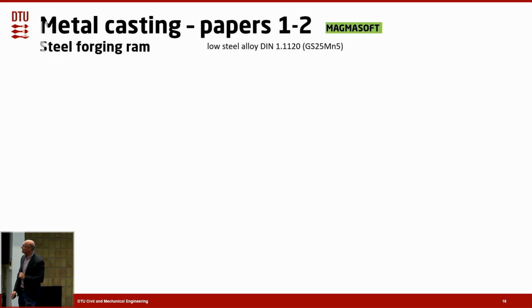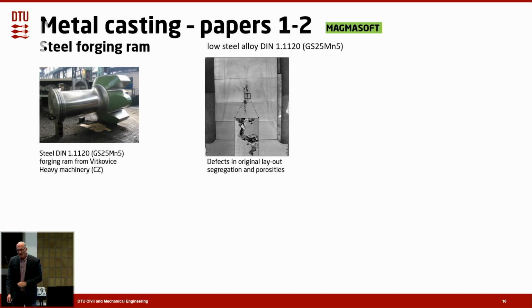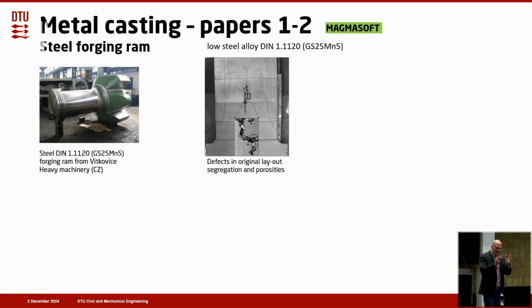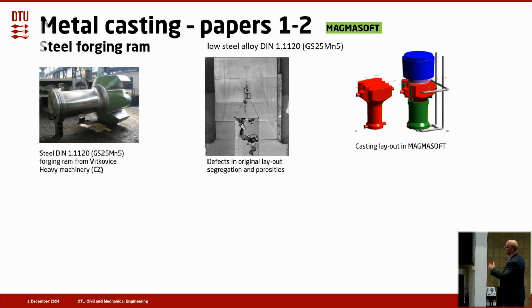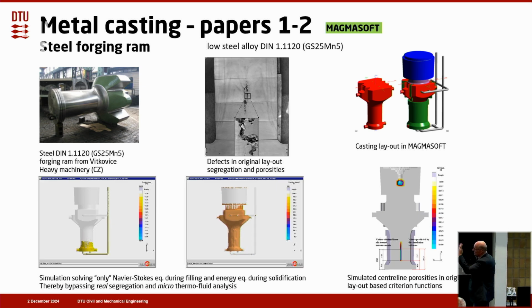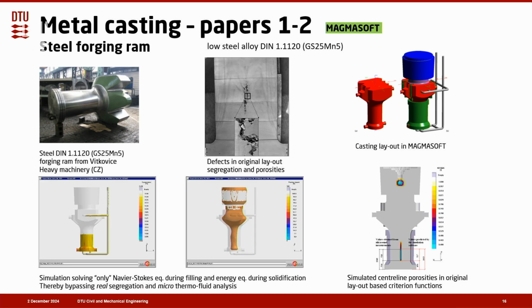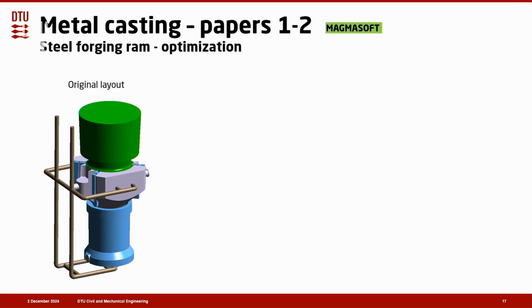So the first two papers were about a steel forging ram. It was a steel forging ram that had centerline porosities as well as segregation. And we did a simulation in Magmasoft to analyze this, and this is what you see here: the fluid flow, the mold filling, the solidification, and that was actually a simplified model as compared to the physics really taking place here. We could predict the centerline porosities. We could also, to some extent, predict the segregation. And then we used this kind of simplified model.